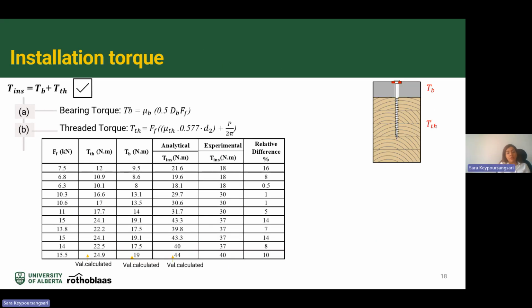So in the second part of step 1, we focused on the installation torque. Because we know that the installation torque is a combination of a bearing torque and the threaded torque. So bearing torque is because of the friction under the head of the screws and the steel plate, and threaded torque is because of the friction between the threaded part and the glulam, and also the shape and the profile of screws will affect threaded torque as well. So we tried to find the bearing torque and threaded torque by using these equations, and you can see the results here. We found the bearing torque and threaded torque by using the force which we found from the load cells, and by which we found the installation torque.